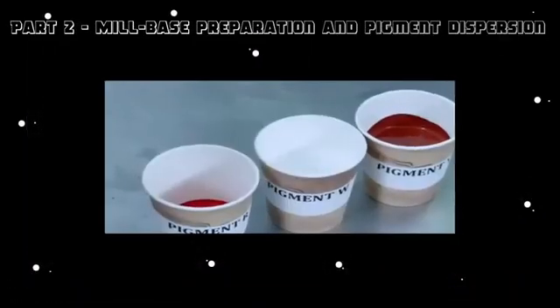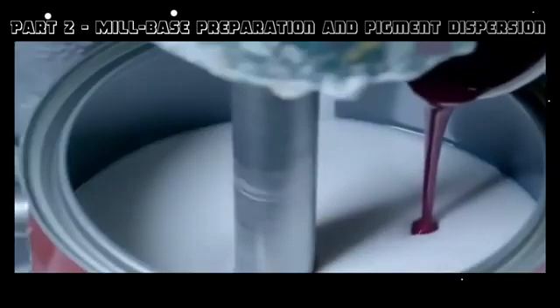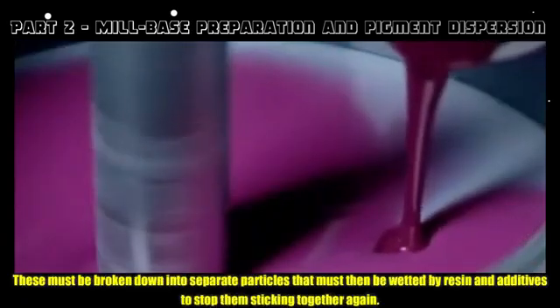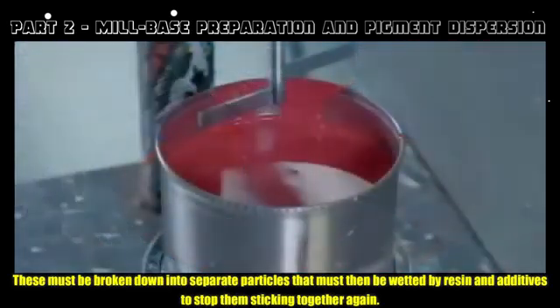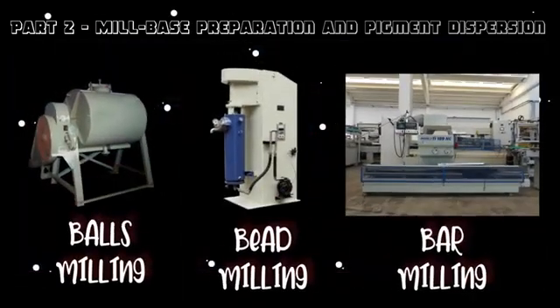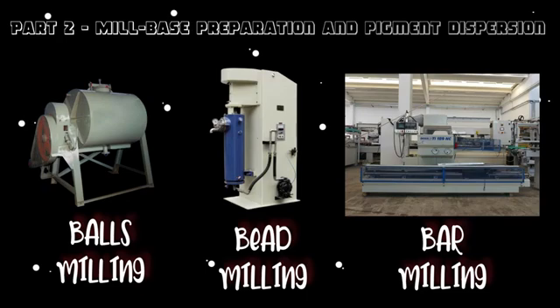Next, prepare the mill base and begin the dispersion process by adding pigments into it. The pigments go through dispersion by breaking down into separate particles that must then be wetted by resin and additives to stop them sticking together again. In some cases, pigments have to be dispersed using ball milling, bead milling, or bar milling.